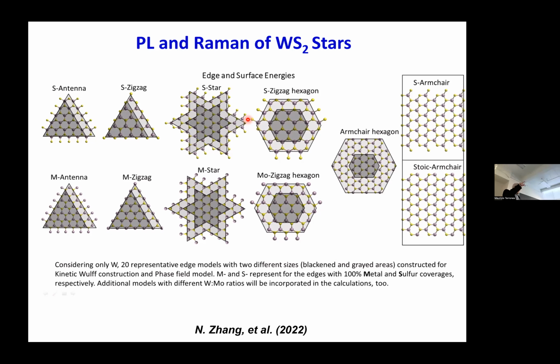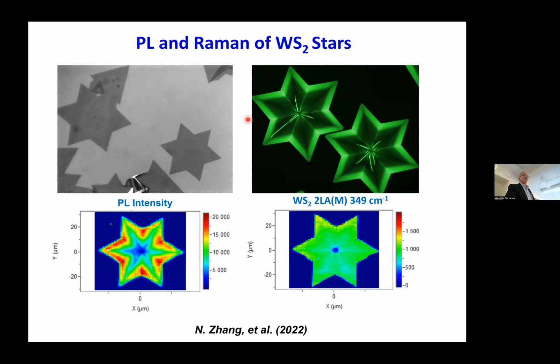So the way we found it is that we started finding, I mean, it took us like 1.5 years to find what was the reason. We could see some stars, and how can we make more? So I told the postdoc we had to make more. Like, no, they cannot, not reproducible. And then we found some moly in the core. And then we started putting moly, a lot of moly, and it was not working. So in the end, we need to add very small amounts of moly. But now it's reproducible, so that's why we can have this.